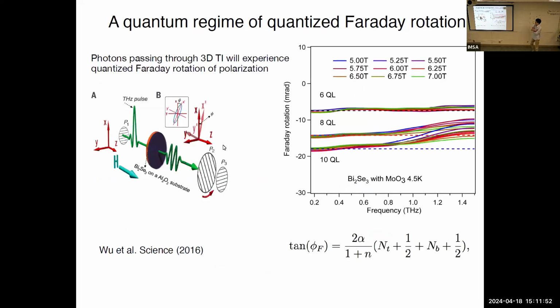Taking all this into consideration, our former colleague measured the exact same thing. So what we do is we send the linearly polarized terahertz light, and then measure by how much its polarization has been rotated after it passes through the 3D TI slab. And here, we show this Faraday rotation as a function of frequency for 3 different samples, and those were 3 different compositions of samples, which also correspond to 3 different filling factors on bottom and top surfaces. And as you can see here, at large enough magnetic fields, this response is getting quantized to these dashed lines, and these dashed lines are the quantized values for this rotation. And you can clearly see that there's a good match between the experimental data and the quantized value, which proves